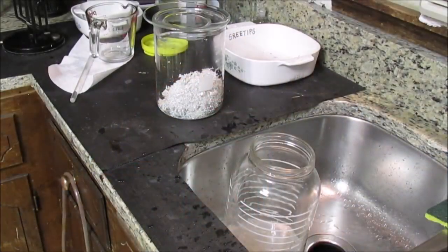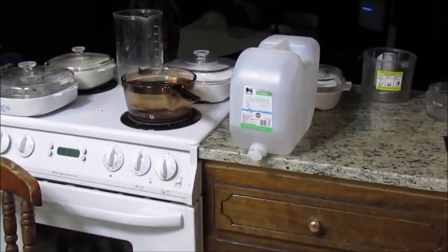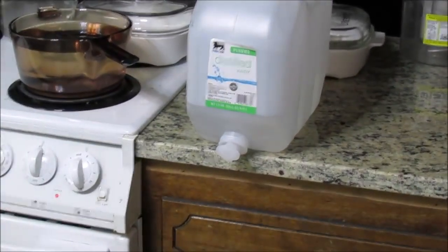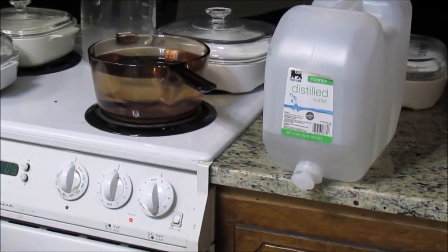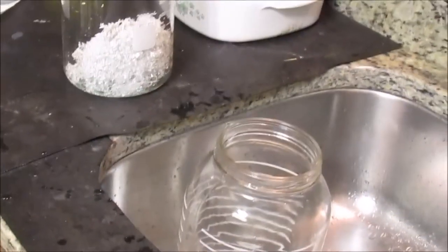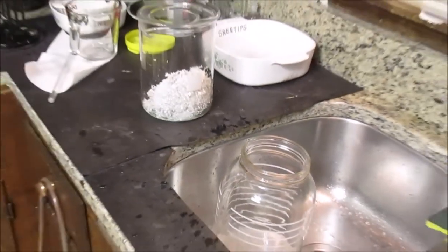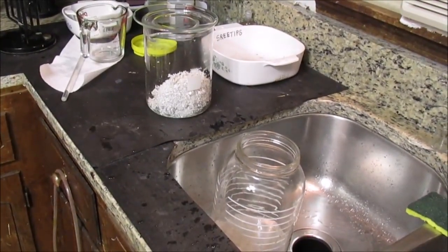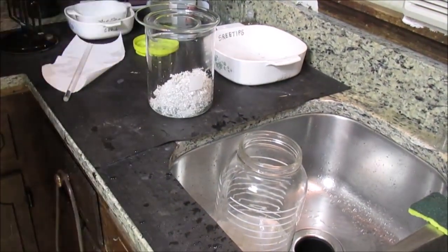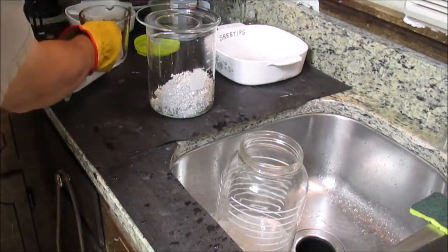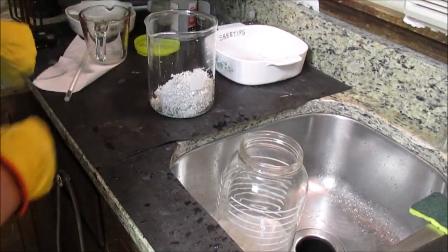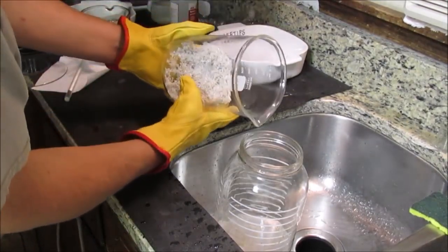I've got our pure silver crystal in the beaker there. Over here I've got some distilled water on the stove. It's actually not boiling, but it's probably up to 180 degrees. It's best to use hot water to do these rinses, I've found. So what I'm going to do is add some of the hot water to our beaker here. First let me pour off all the electrolyte that I can.